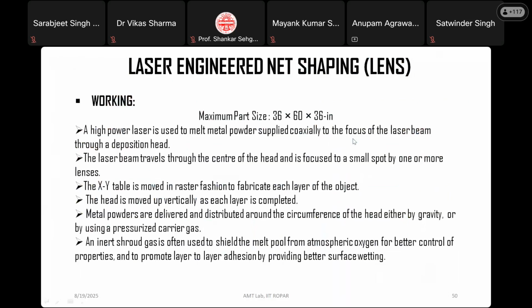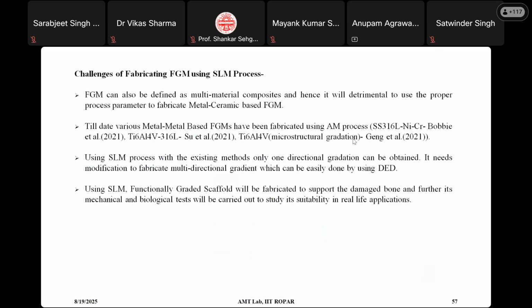However, when we are making this FGM, functionally graded material, using the SLM process, even though we are able to process one layer at a time, and engineer the material properties within the layer itself, the challenge is that if the metal and ceramic are mixed together, to date we do not have the kind of facility which can vary the laser intensity at every point. Ideally we should be able to vary the laser intensity at every point within the layer if we want to fabricate that very nicely.